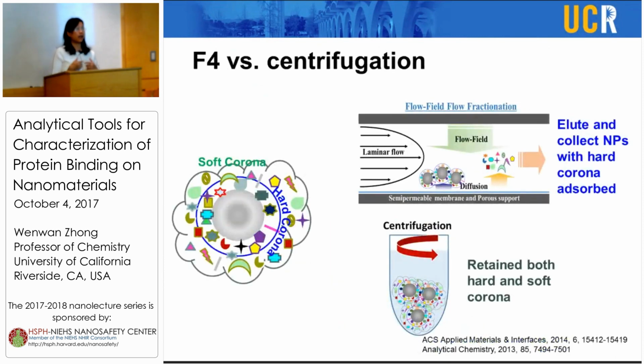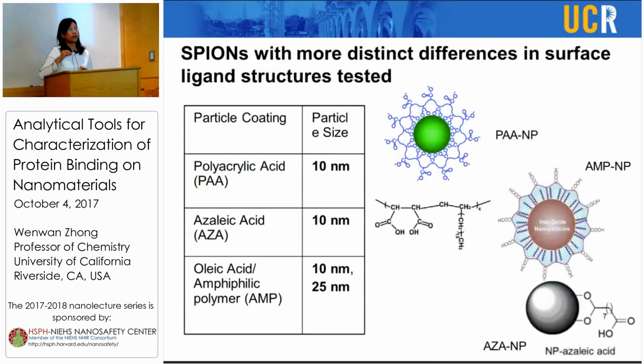Because for centrifugation of these nanoparticles, if we don't use a very strong ultracentrifuge, just a tabletop centrifugation device, it would take a little bit longer to sink down all the particles. So during that time, both the soft and hard corona could be maintained. So when we compare the proteins identified on the particle from centrifugation and also from the particle collected from our flow field fractionation technique, we will find out what are the ones that belong to soft and what are the ones that belong to hard.